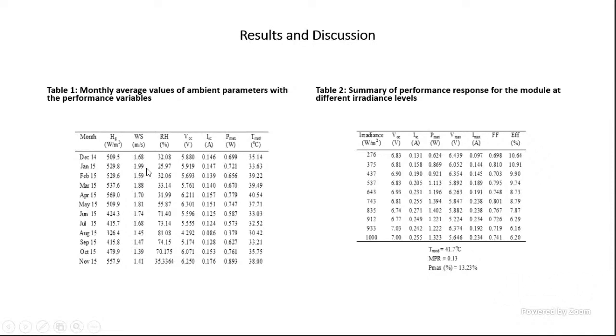And in comparison with February, which has almost the same irradiance as January, we can see that the wind speed favors open circuit voltage, because when the wind speed is high, there will be rapid transfer of heat from the module to the ambient, which invariably cools the module. And then you see that the high wind speed favors the open circuit voltage better than the short circuit current vis-a-vis other factors.